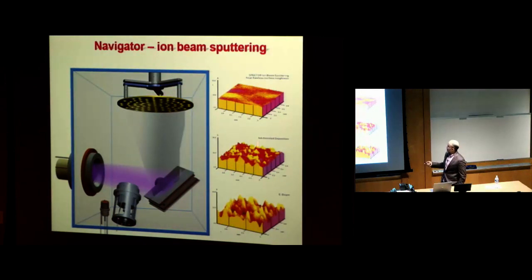Here is an example of why ion beam sputtering is better than an electron beam machine. This is how the roughness of our coating looks if we use electron beam machines, because the energy of the material which flies in the direction of the mirrors is very low. We have quite a rough surface. As a modification of electron beam machines, people invented a machine with ion assistance. It means that additionally they bombard the material with an ion gun. In such a way they are able to pack the material more densely. It's better than a pure electron beam machine, but if you compare the result with an ion beam sputtering machine, it's just incomparable, because the layers from an ion beam sputtering machine are much smoother.